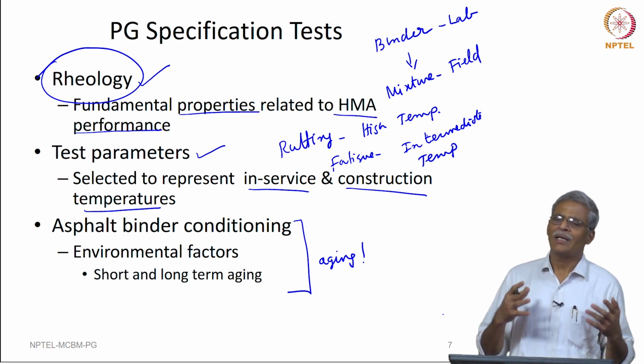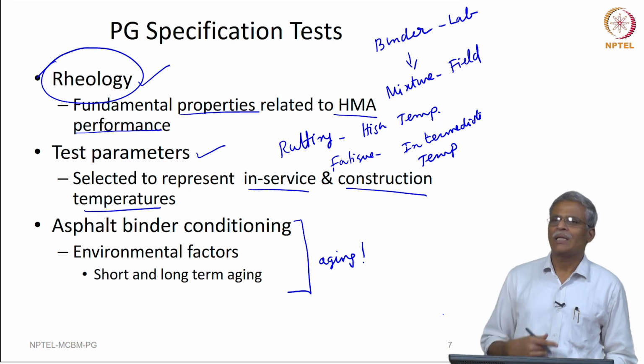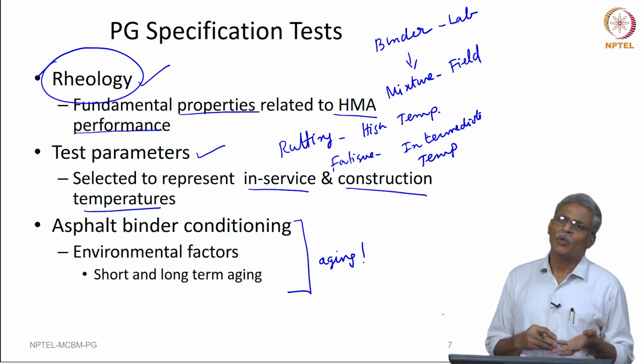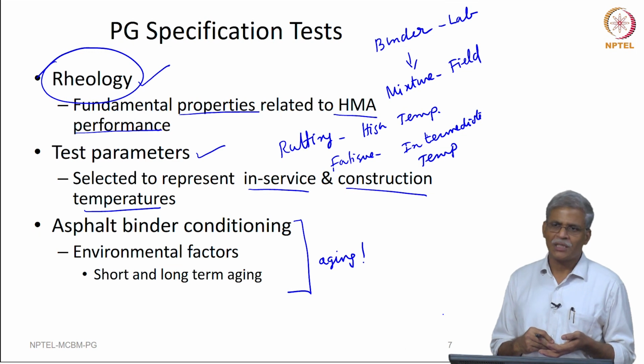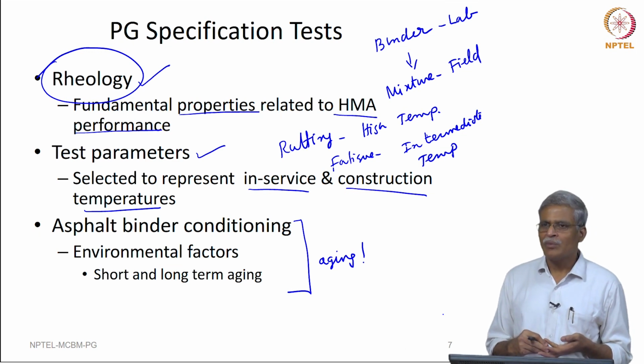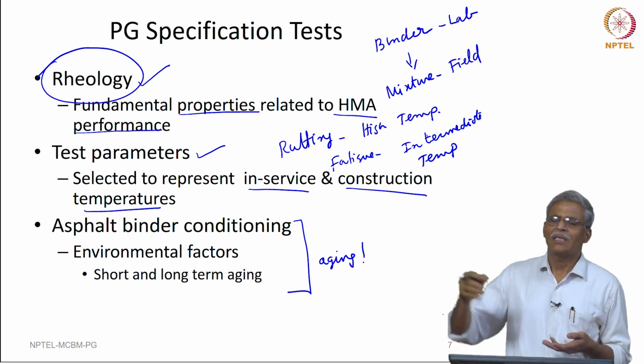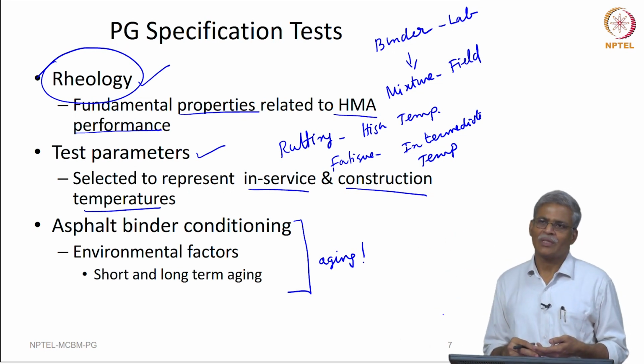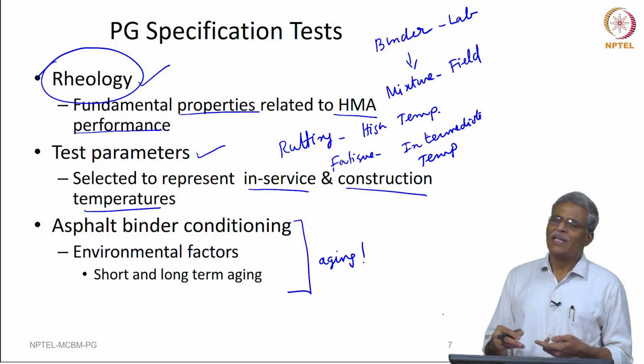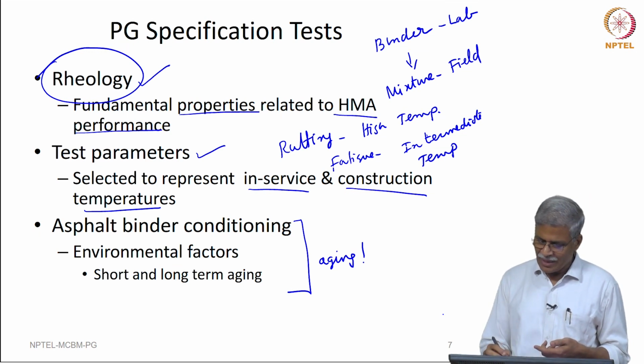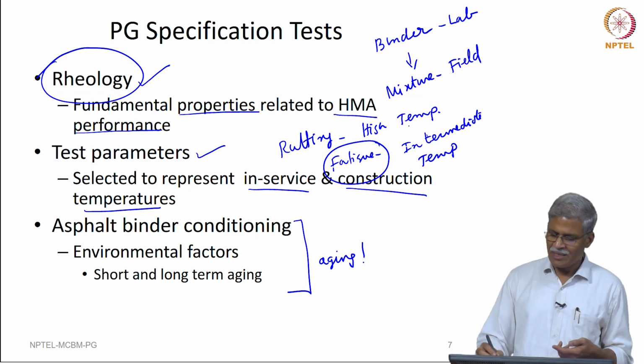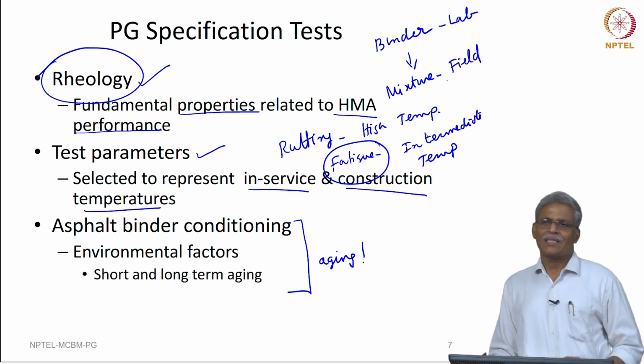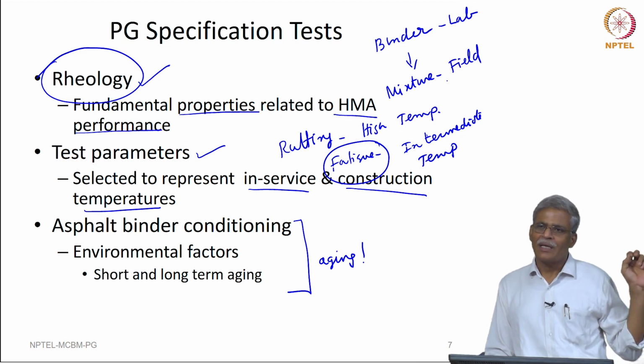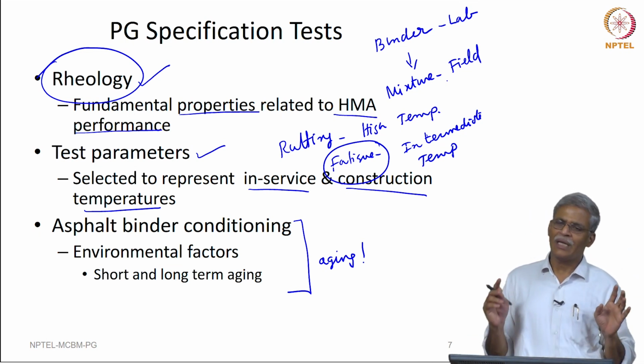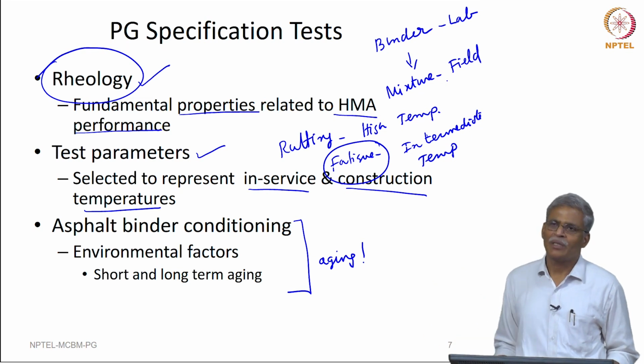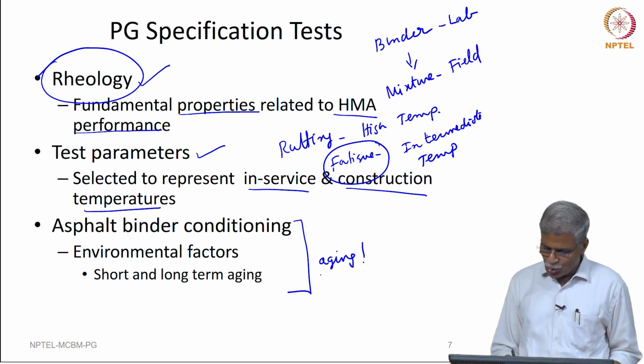and we also need to realize that as the pavement is constructed and it is in service, the property of the material keeps changing. So, there is going to be a short term aging due to the construction. There is also going to be a long term aging because of the service conditions, due to the weather as well as the traffic condition. So, if I am really interested to find out the fatigue response of a binder that in essence could be related to the mixture, it is necessary that the binder should be age hardened in the laboratory to simulate what can really happen in the field condition. So, this also should be considered.